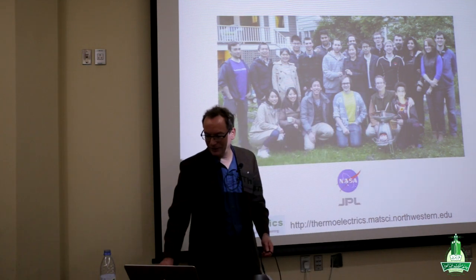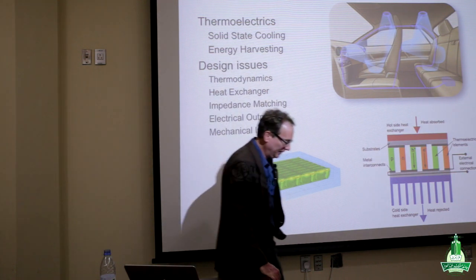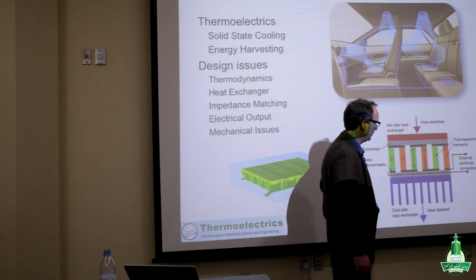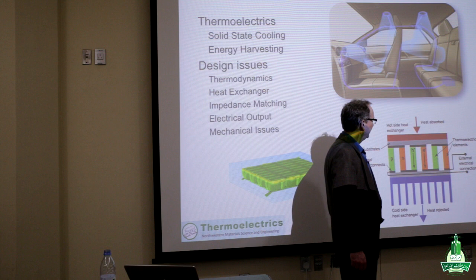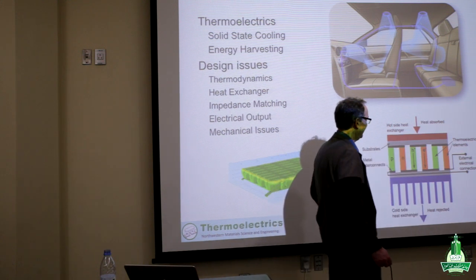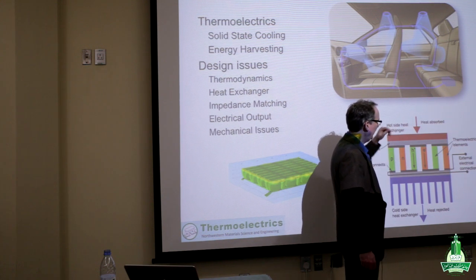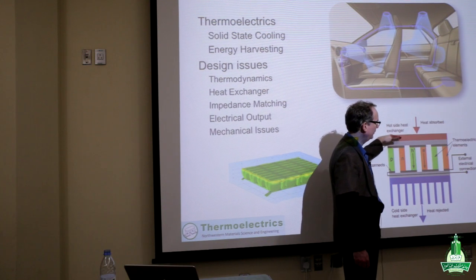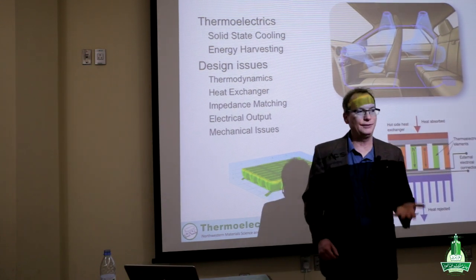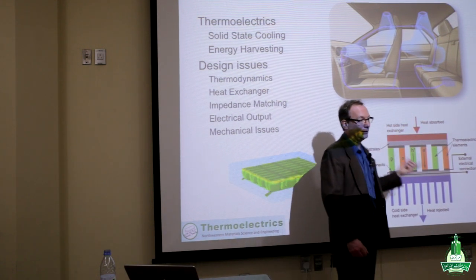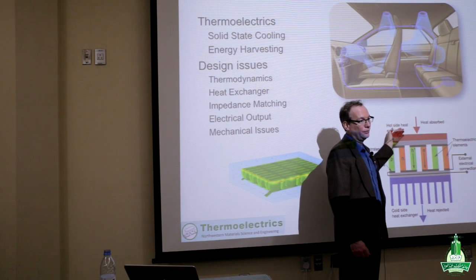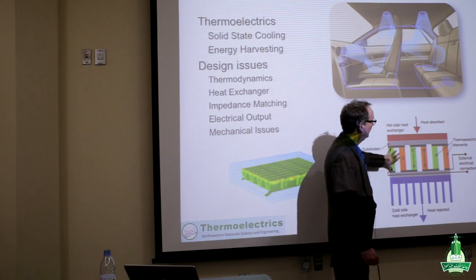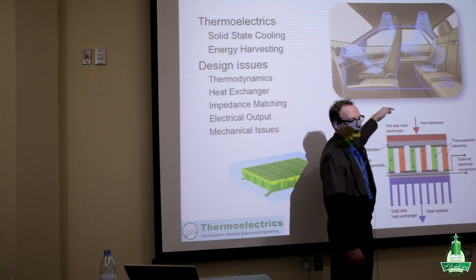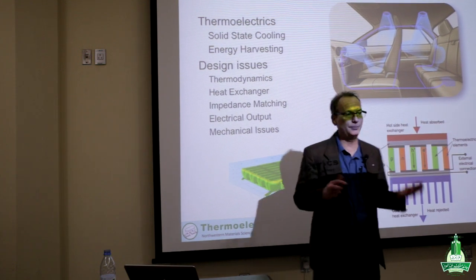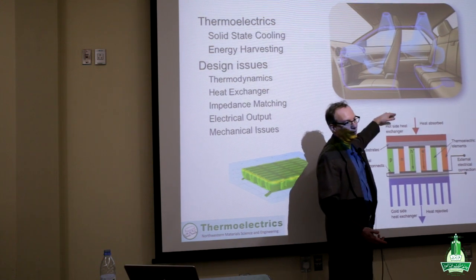Yes, so this has been an idea that comes up. There are a number of different ways to solve this, and the real problem is the photovoltaic collector. If you use a standard silicon photovoltaic device, the efficiency of the photovoltaic depends on temperature. The silicon ones in particular have lower efficiency as they get hotter. But the thermoelectric needs a hot heat source to be efficient. And so there's a bit of a trade-off as to what temperature you would want this junction to be.